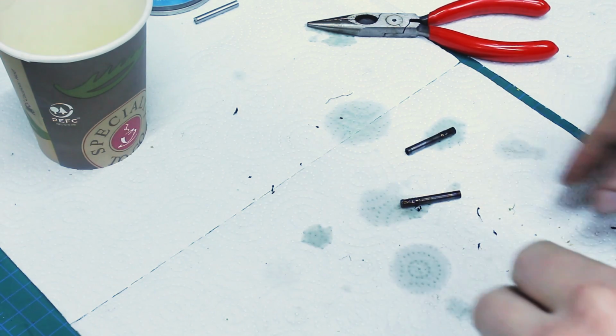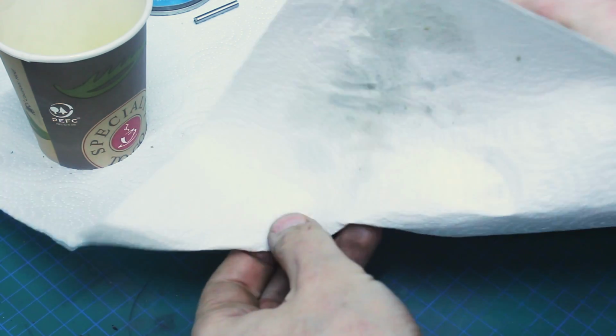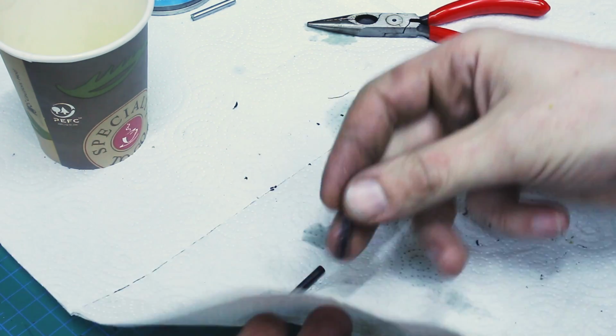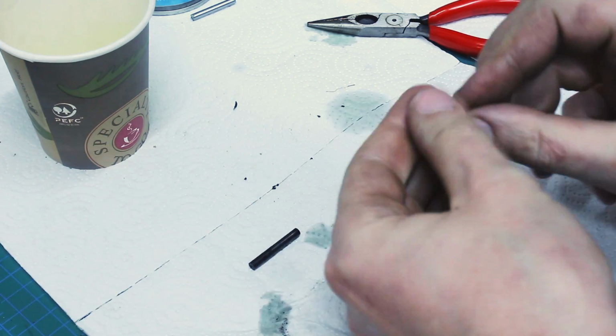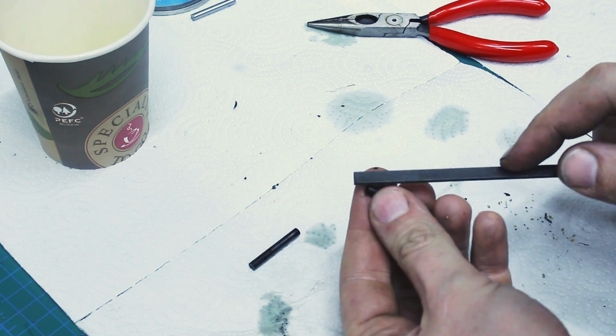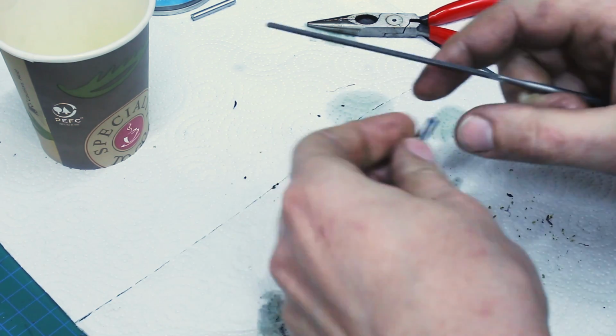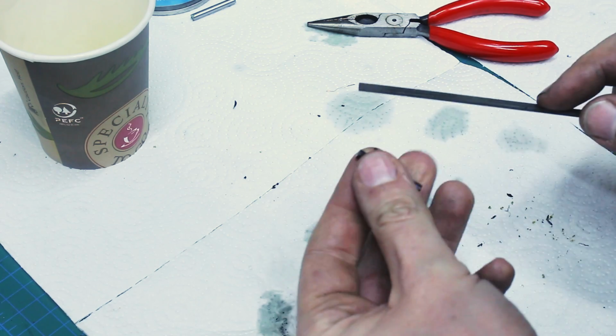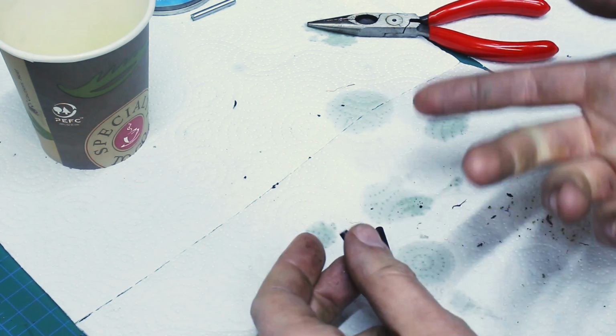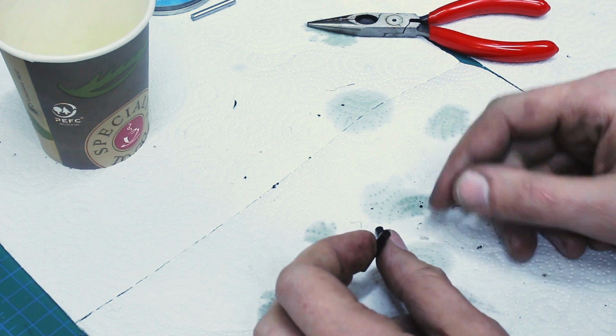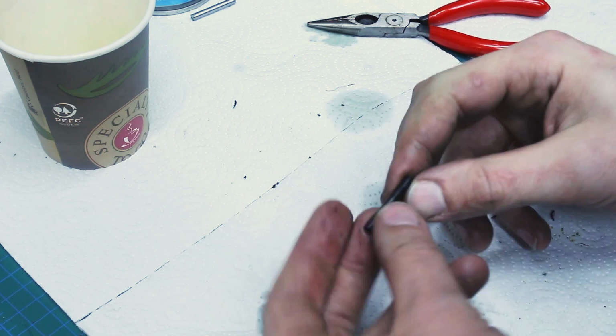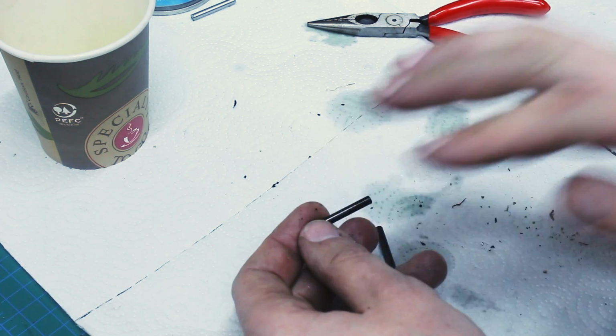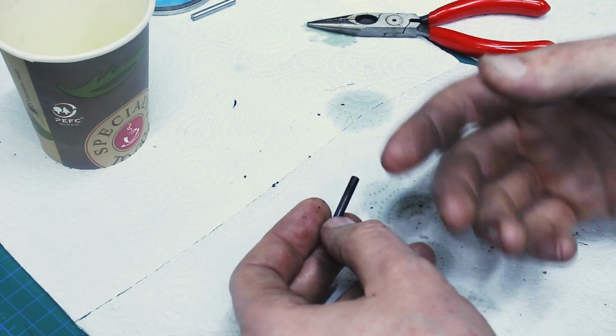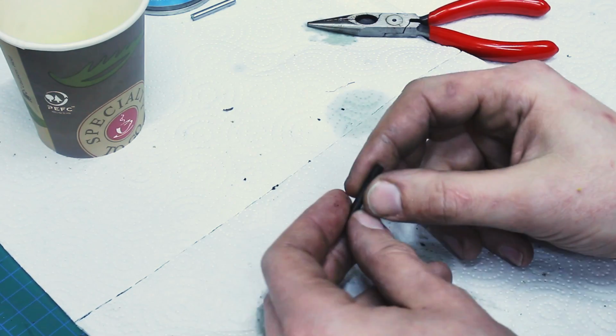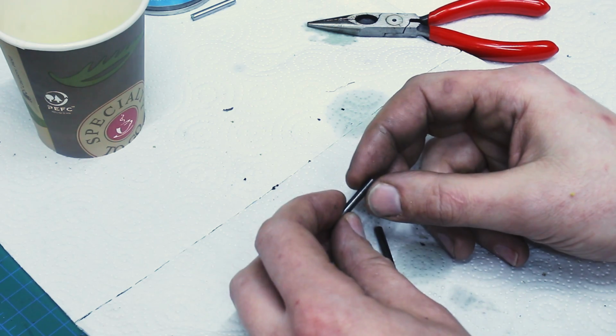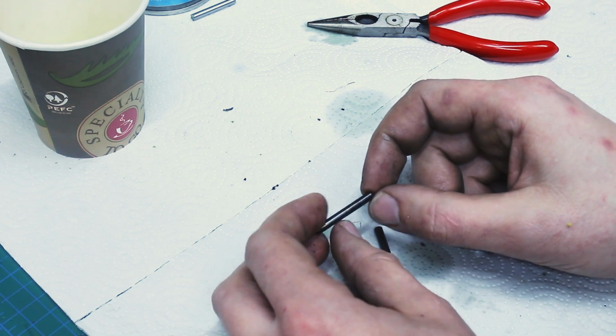I'm not going to put them under the hardness test because I don't want diamond indentations on them. But we can check with a regular file here, with needle file. And that's hard. Drill rod is one of the easiest to harden tool steels. The steel is now fully hardened. This is the maximum hardness the steel will get with this type of quench. But also there is a ton of stresses in them, and this is very much prone to cracking.